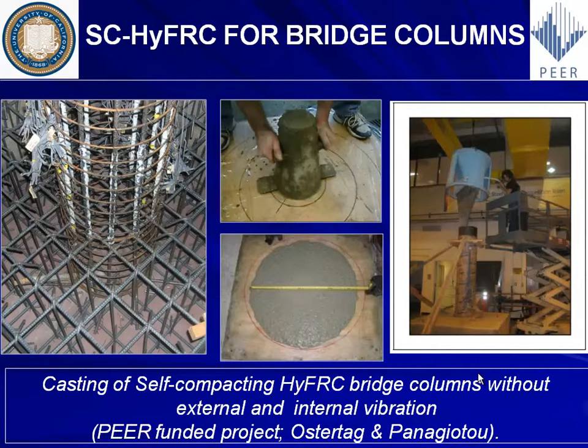It was funded, by the bridge column, which was funded by PEER. We used here self-compacting, and if you're not familiar with it, you do the slump test like before, but then you have a pancake afterwards. But you have to make sure that this pancake is very nice and round, because you want to have a very cohesive mix. So you don't have any separation between the matrix, between the paste and the aggregates, and the paste and the fibers. That kind of mix doesn't require any vibration, no internal vibration, no external vibration. It's very, very easy to flow in between these very congested areas right here.